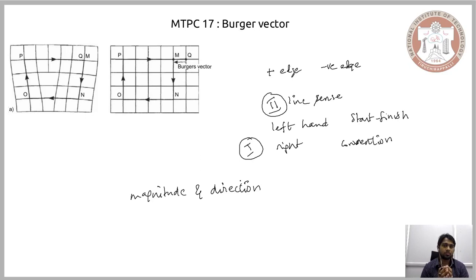We also saw how we can calculate the magnitude alone based on the Burgers vector. So we take the position of the atom or the interatomic position for each of the coordinate axes, we square it, and we take the square root of the overall term. Since we have considered BCC in the previous lecture, let us consider FCC here.